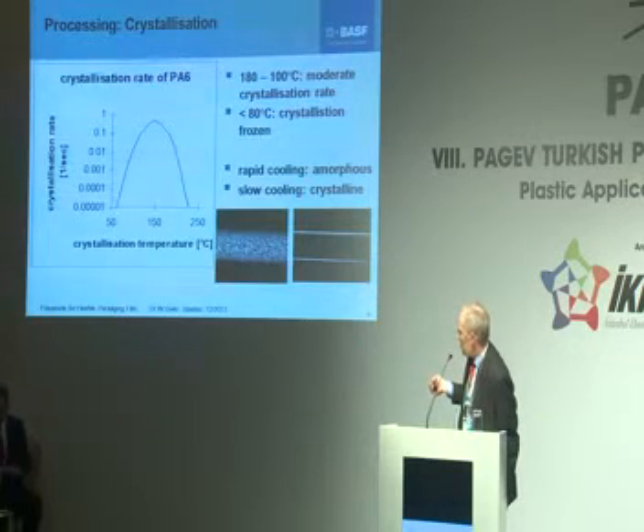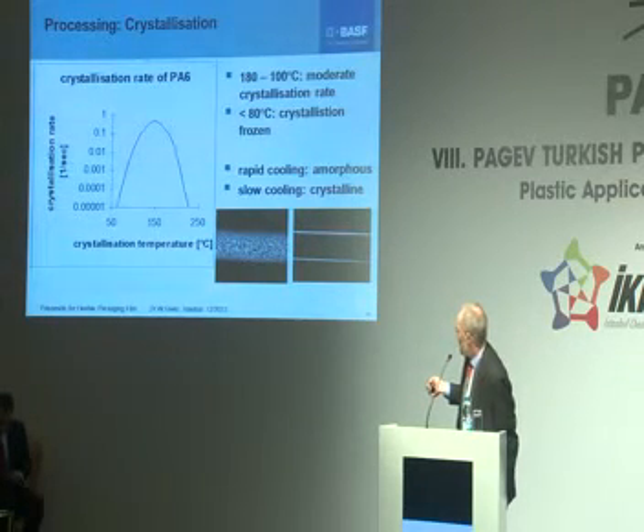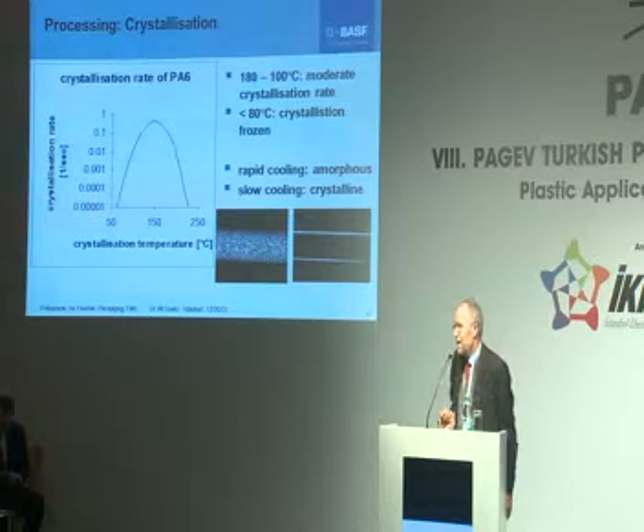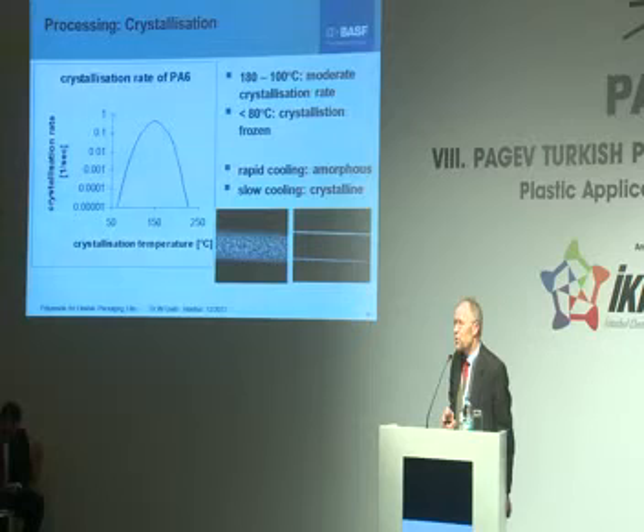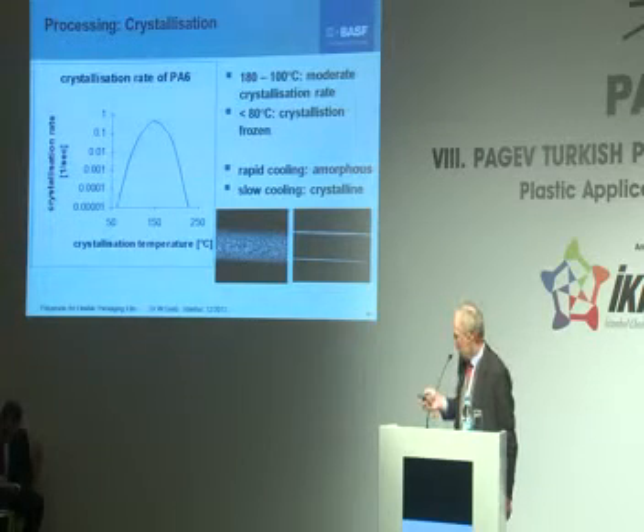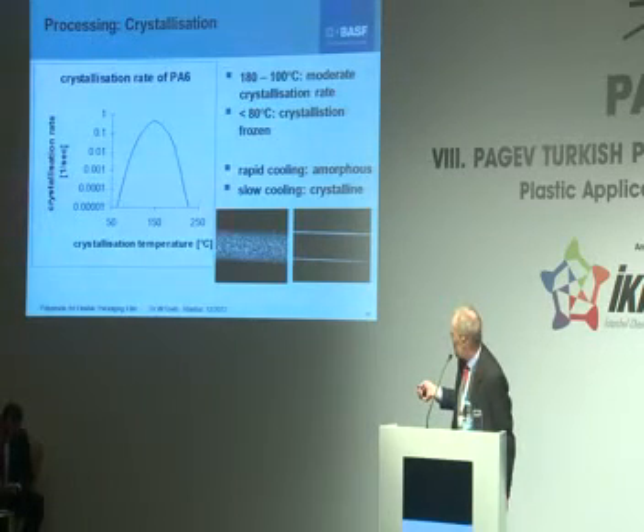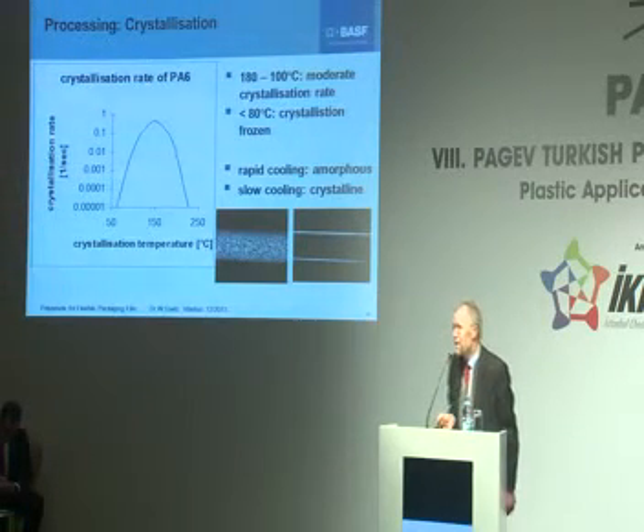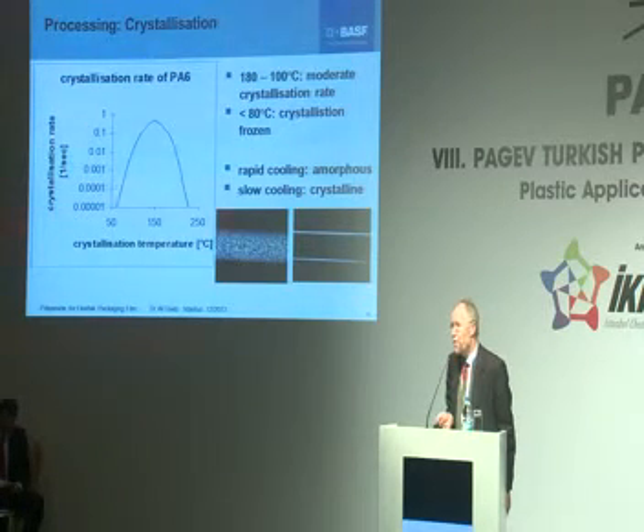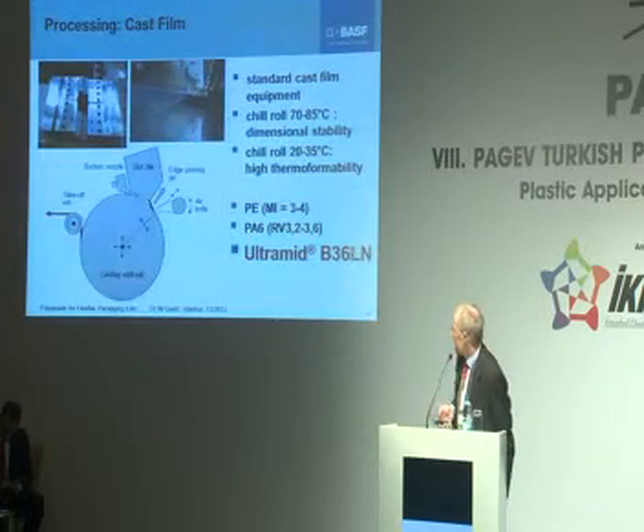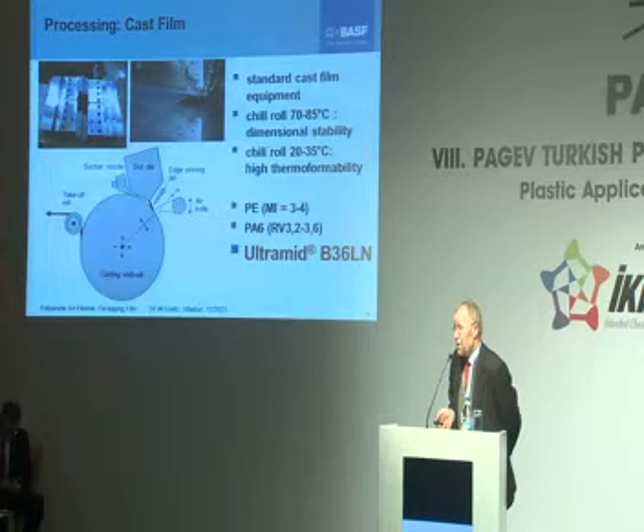A pretty amorphous film can be obtained by quenching the film so fast that it has no time to form crystals while in the temperature range where the crystallization speed is fast. Or on the other side, by cooling relatively slowly, permitting a long residence time in the range of crystallization, a highly crystalline film with visible crystals is produced. Polyamide is produced by both cast and blown film.